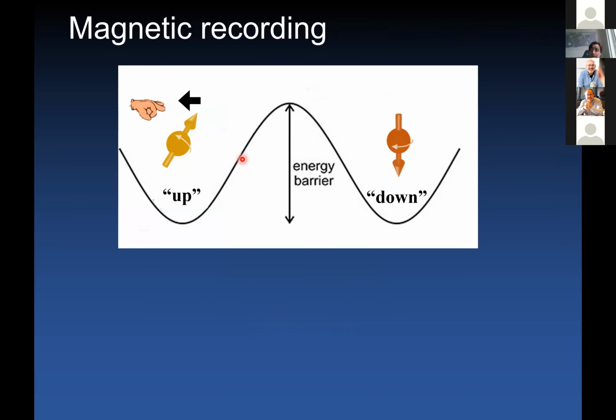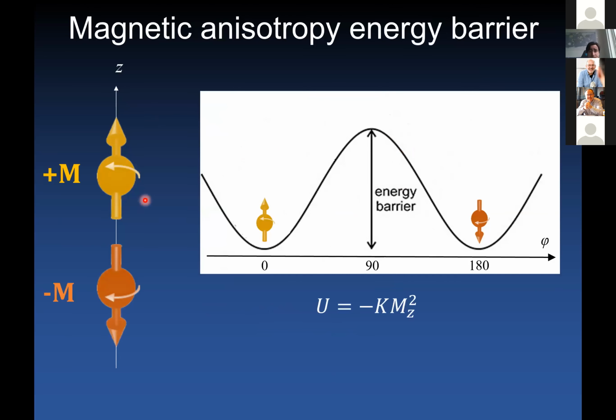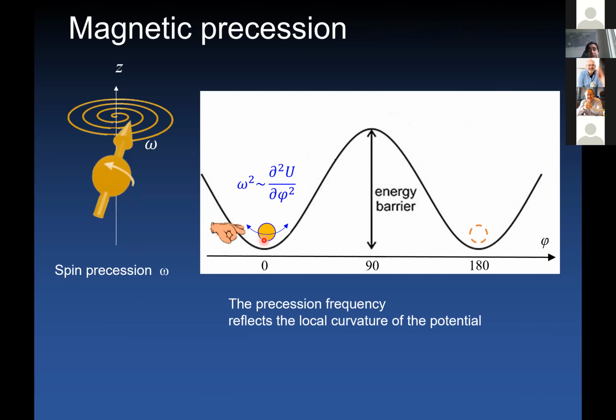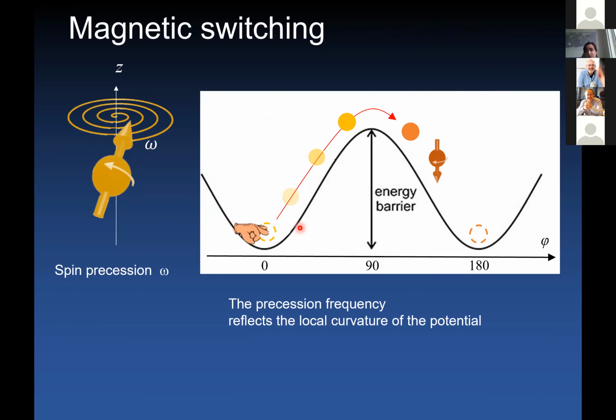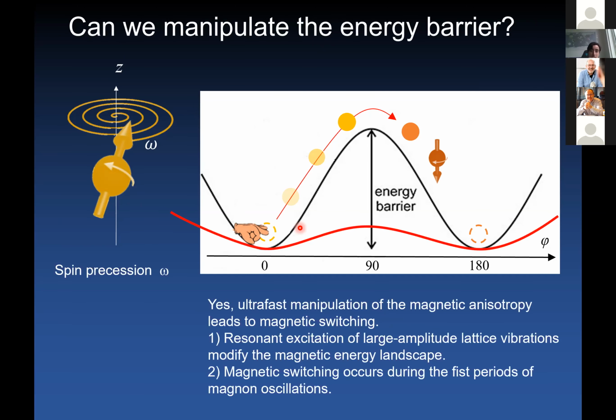So this is the idea, and this is relevant for the problem of magnetic recording. When you want to switch a magnet from an up state to a down state, you need to overcome a certain energy barrier, and the size of this energy barrier is not set by the exchange interaction, but rather it's set by the magnetic anisotropy. That's what defines our energy barrier. And typically this is done in ferromagnets by exciting spin precessions. So by exciting precessions of the spins, you can kick this ball across the energy barrier and switch from positive to negative. So these are coherent spin precessions that are typically induced in microwave experiments. And the precession frequency reflects the local curvature of the magnetic potential. If these precessions have a sufficiently large amplitude, you will be able to overcome the energy barrier and to go from one state to the next.